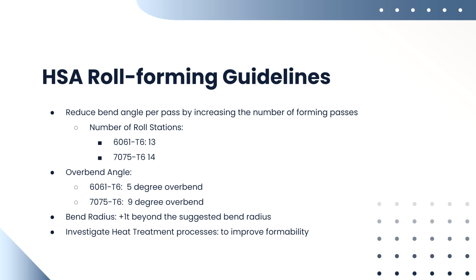Based on the test results and simulations, the team has developed the following guidelines for roll forming high-strength aluminum. It is recommended to reduce bend angles per pass by adding more passes. More roll passes can help to mitigate cracking, residual stresses, and longitudinal bow. The recommended minimum number of stations for 6061 T6 is 13, and for 7075 T6, 14.